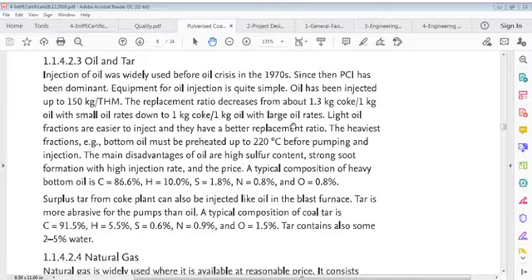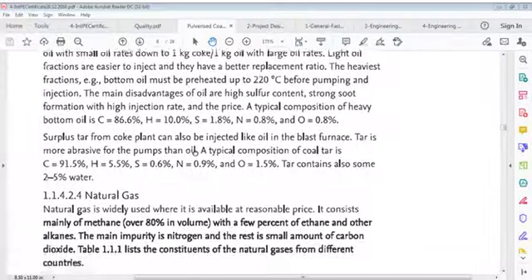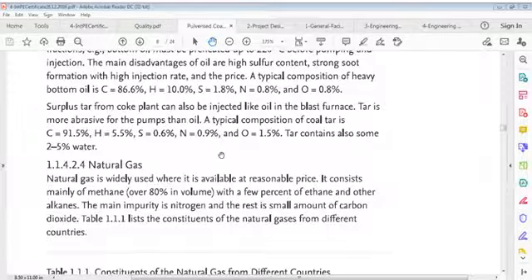Light oil fractions are easier to inject and have a better replacement ratio. The heaviest fractions, bottom oil, must be preheated up to 220 degrees Celsius before pumping and injection. Main disadvantages of oil are high sulfur content, strong soot formation at high injection rates, and price. A typical composition of heavy bottom oil is C = 86.6%, H = 10%, S = 1.8%, N = 0.8%, and O = 0.8%.